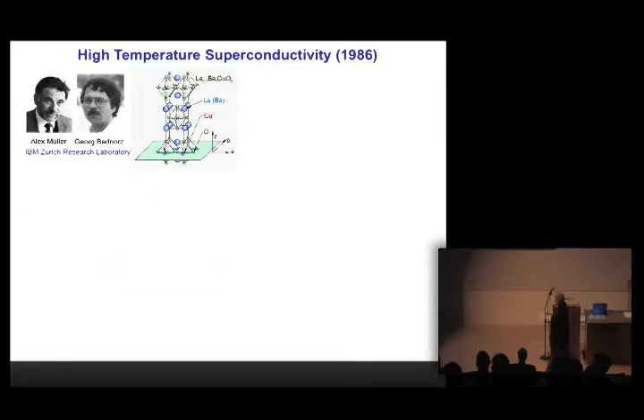So everything changed in superconductivity in 1986, when the discovery of these high-temperature superconductors by Alex Mueller and Georg Bednorz at IBM Zurich really set the world into a tizzy. This is a material lanthanum barium copper oxide. It had a TC only a little bit higher. It was about 30 Kelvin, a little bit higher than the niobium-3 germanium. But within even a few weeks, the TC had shot up precipitously up to around 150 degrees, I think under pressure is the highest temperature so far. The important line to look at here is this one. This is the liquid nitrogen line. So once you can have superconductors at liquid nitrogen, you can think of all kinds of applications, you can levitate magnets in front of yourself, in front of your face in the laboratory, and the whole world really changed.